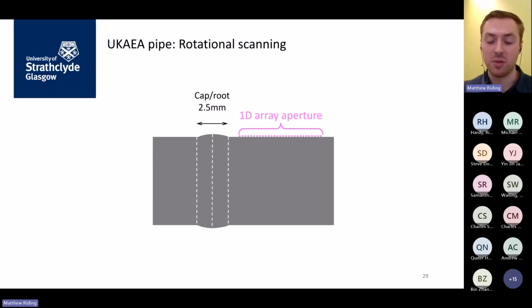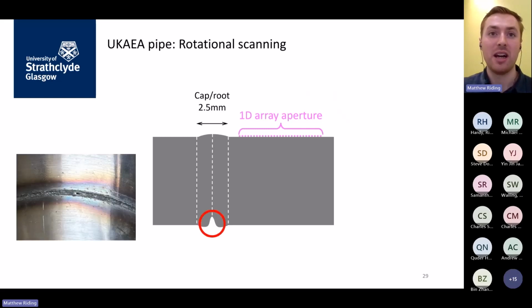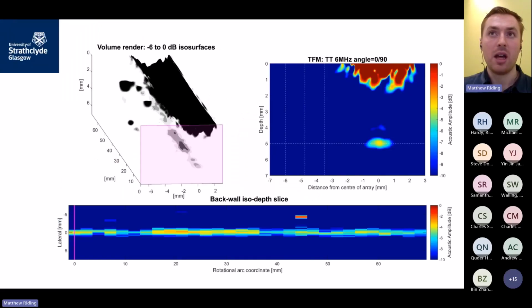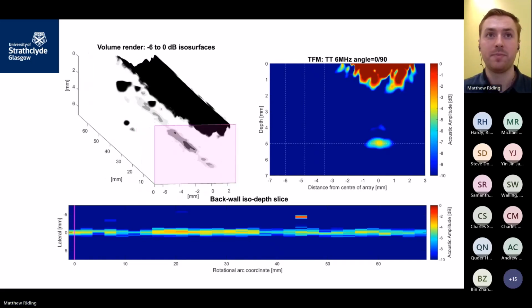So we're forming an aperture to one side again of the weld cap on the outside. We're looking for a defect down at the weld root. So I'm going to present all of the images we've captured stacked into a 3D volume in the top left, and then it's going to step through each image individually, highlighting with the magenta plane, and it will display that corresponding image in the top right. The bottom plot is a slice through the 3D volume at the depth of the back wall. There's one outstanding indication, and I hope it will be clear to you when I play the animation.